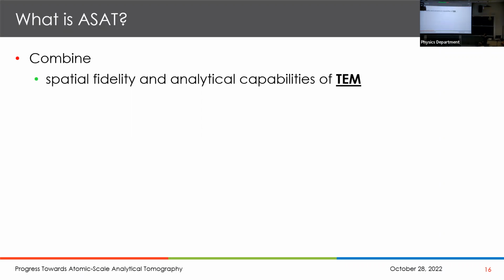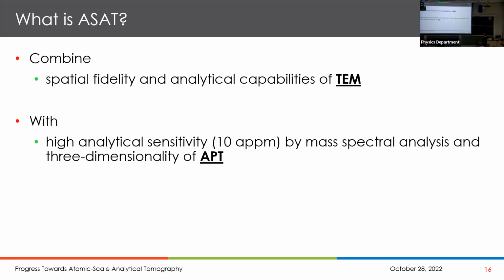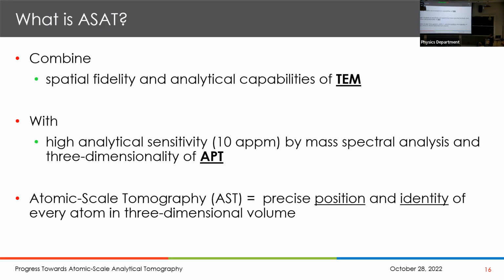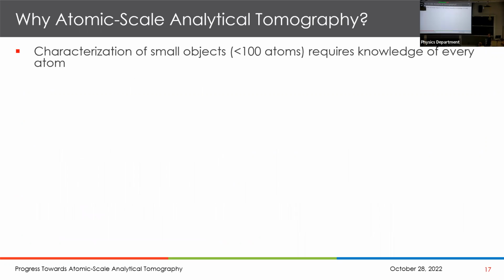So what is atomic scale analytical tomography? Well, if we could take the best of TEM by combining its spatial fidelity and analytical capabilities with the high analytical sensitivity by mass spectral analysis and the three-dimensionality of the atom probe, or atom probe tomography, then I would call that atomic scale tomography, if what you're really after is the precise positioning and identity of every atom or isotope in this three-dimensional volume. We might also add that if you take the analytical information from the TEM, like the yields, and this is very important, I would call that atomic scale analytical tomography, or ASAT. So there's the definition. And then the question is, how do we get there? And who cares if we do get there? So this one slide looks at some of the things that you can do that would require that, or where this information would be valuable.